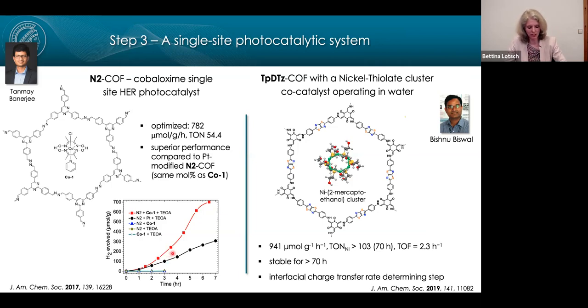to tackle and change. And so we developed this system here, a thiazole COF that we combined with a hexameric nickel cluster co-catalyst that is actually assembled in situ. And so this system here works in pure water. It works very stably. It's actually even more efficient than this cobaloxime system here. And so we modeled the reaction by using a microkinetic model. And what we found out, and this is not too surprising, is that the electron transfer step from the COF to the co-catalyst is the rate limiting step most likely.